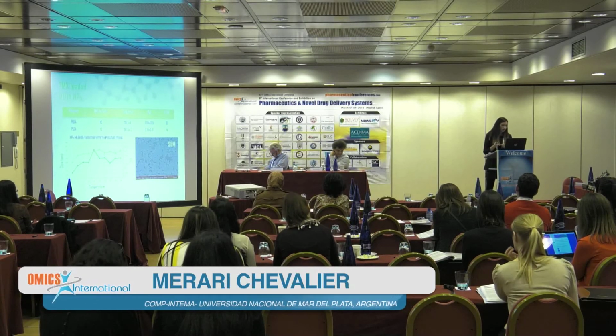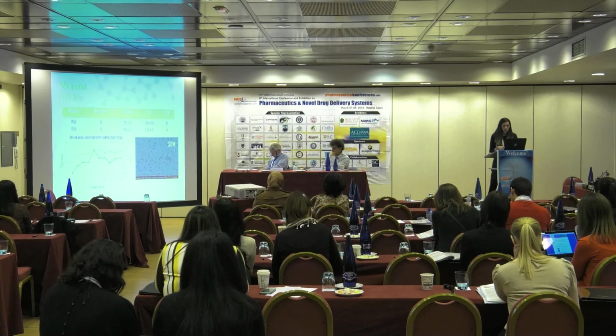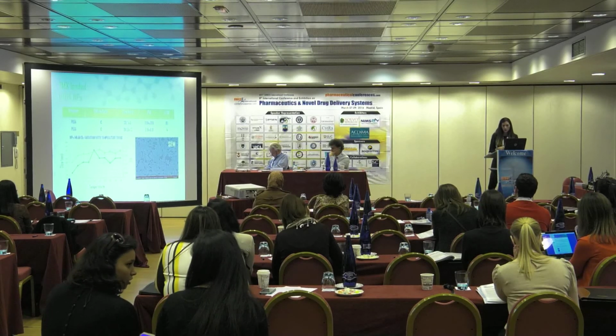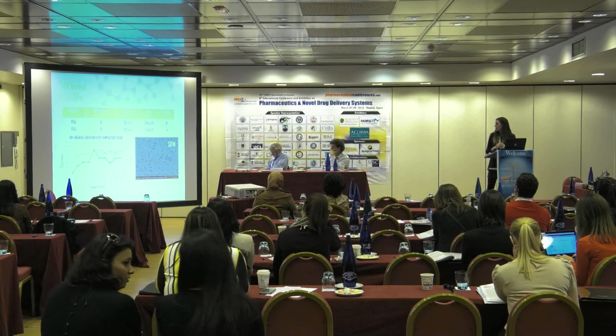With 10% of tamoxifen in relationship with the mass of the polymer, we get particles around 200 nanometers, and with a really good polydispersity. The encapsulation efficiency could be improved because we started the synthesis not so long ago, so we will try to optimize it because we know that we can reach 80% in encapsulation efficiency.